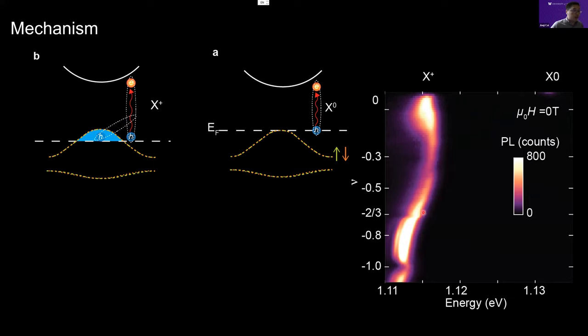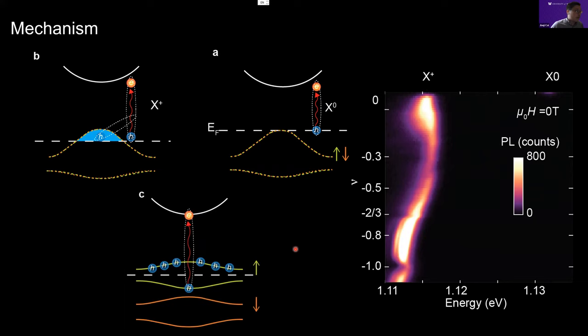And as you dope into those correlated states, what happens is that the strong electron-electron correlation actually gaps the system out, and there are no holes anymore on the Fermi surface. Only a very small population of thermally excited holes can be bonded with the exciton. So you see a sharp reduction of the trion population.